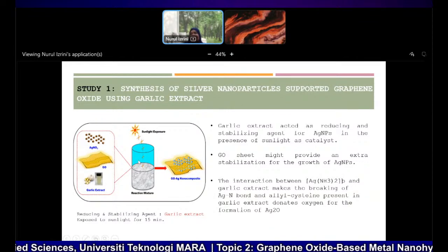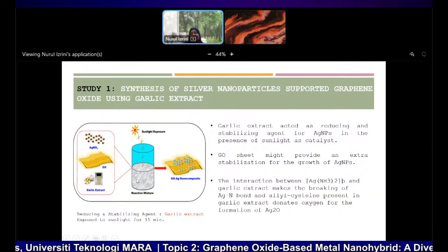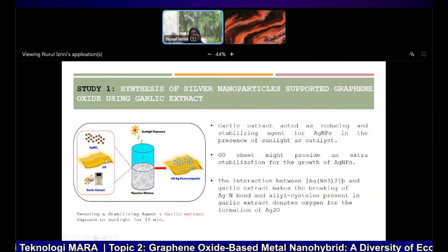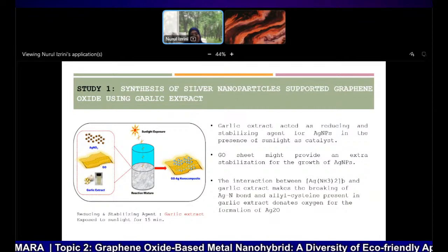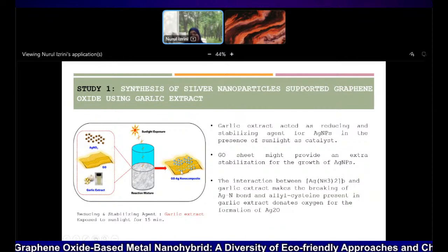This is a very simple reaction method because we just expose the samples to sunlight for just 15 minutes. After 15 minutes, we can form good formations of GO-Ag nanocomposites.